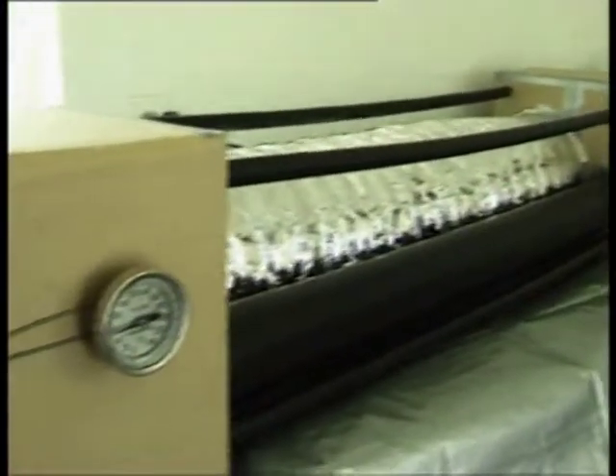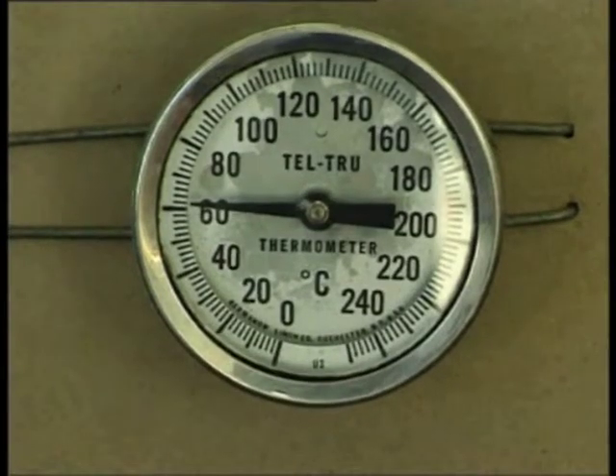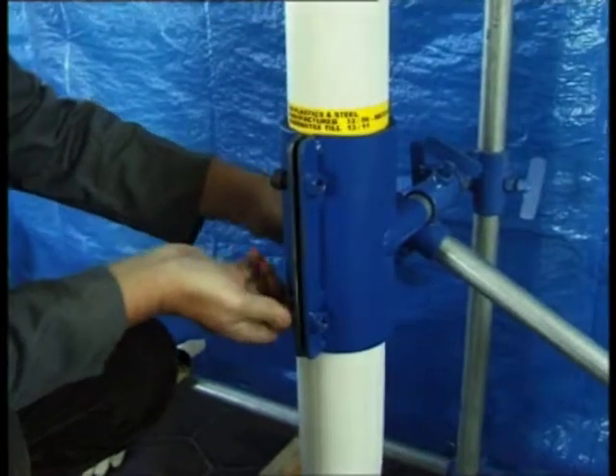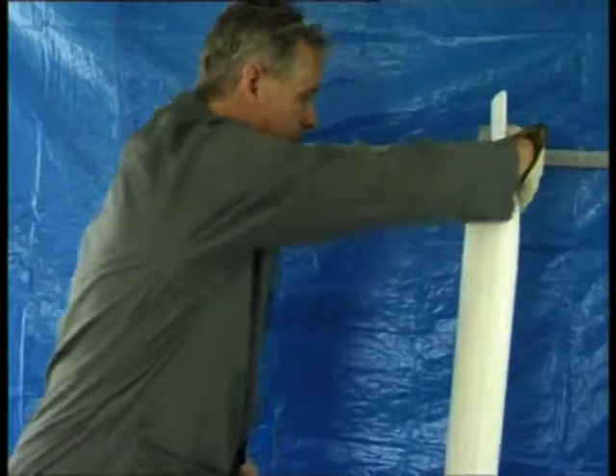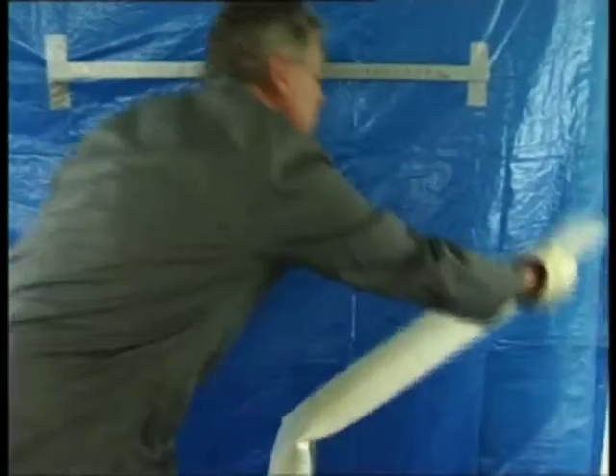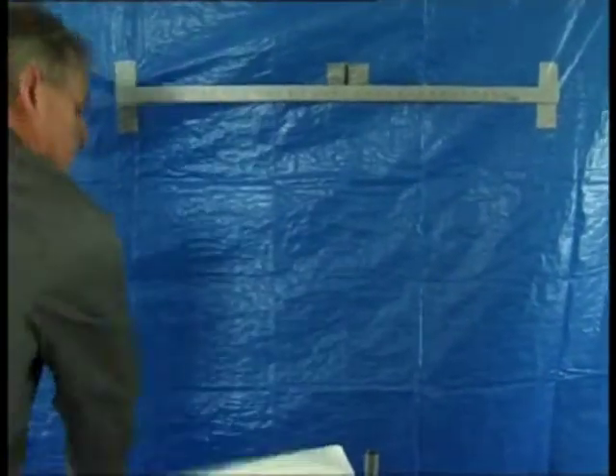Each post was treated to 60 degrees Celsius for 2 minutes in accordance to the standards. They were removed and clamped into a suitable clamping device. Within a period of 2 minutes from removal, the test was carried out. The post was bent in the line of traffic direction at 90 degrees. The post was then bent 180 degrees from this position. This procedure was repeated 3 times.